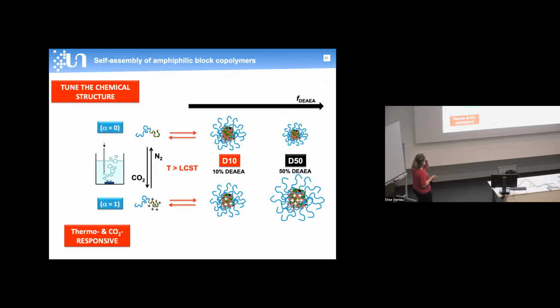So in general, what is interesting with this system is that it's also a pH and thermoresponsive system, but in this case, the aggregation can be tuned by the bubbling time of carbon dioxide. And again, it's very interesting because you avoid the accumulation of acid and base, which would influence the aggregation behavior in solution.